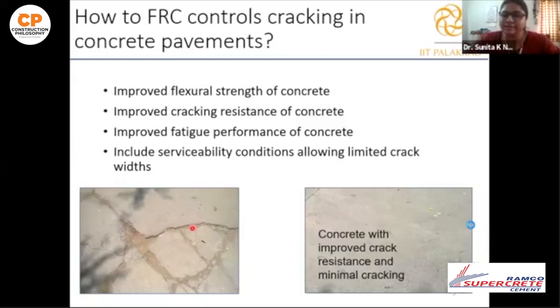Now you can see that there is a crack, even in the FRC, you can see a crack. It's almost of the same age, but the crack width is so minor that it does not affect the serviceability at all. So this is also possible. This is imparting an inherent cracking resistance capacity to concrete. This is one of the strategies that you can adopt.